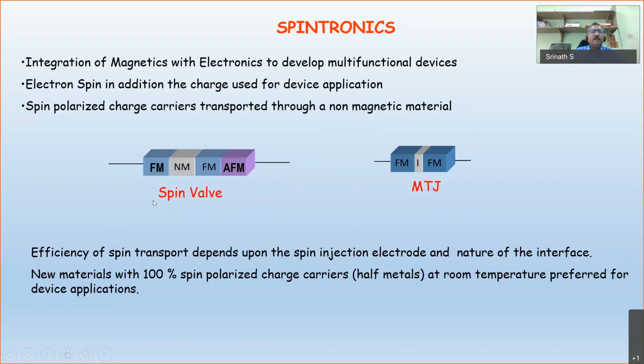For that, the device structure is like this. I will have a ferromagnet in which the spins are all pointing along one direction, let us say. Another ferromagnet, in which again the spins are all pointing. But this ferromagnet is coupled with an antiferromagnetic layer. So this is called the pinned layer. And this ferromagnet is separated from the other ferromagnet through a non-magnetic spacer. So you have a spacer, and this is a free ferromagnetic layer. There is a spacer, and there is another ferromagnet, but this ferromagnet is not a free layer, it is coupled with an antiferromagnet. So this fellow's magnetization is now coupled with this fellow.